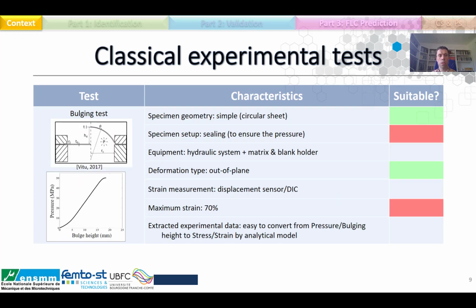We also used some bulging tests, but as our strips are very small, we need to develop a new setup for this experiment, and the size is very small. So the sealing will be very hard to obtain to apply the pressure, and in copper alloys, the maximum strain is just around 70%.